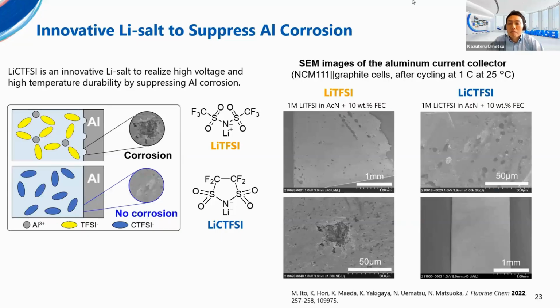Okay, by the way, let me introduce LiCTFSI as a next generation lithium salt. For example, linear imide salts such as LiFSI and LiTFSI increase the ionic conductivity of electrolytes and improve low temperature performance and durability of lithium-ion batteries, but are known to corrode the aluminum current collector under high voltage conditions. To prevent this, it is common to mix a fluorine source such as LiPF6 into the electrolyte to form a protective layer on the aluminum foil.